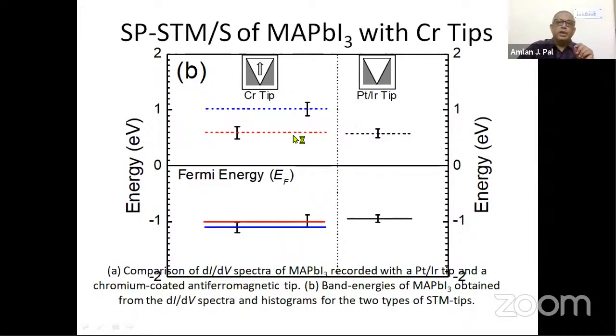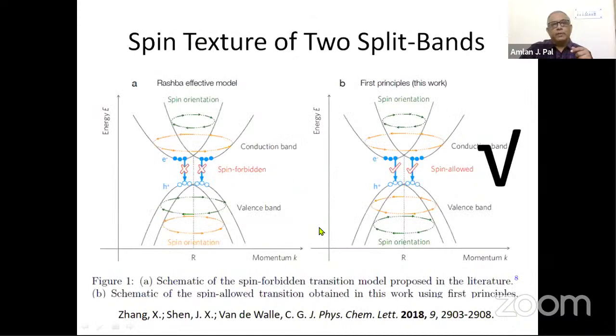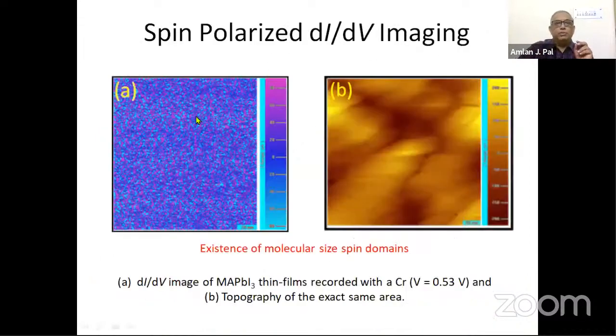We found that if we do one measurement, we get these red levels, and in the next molecule, we see the blue levels. That is, the domains are just molecular in nature. That is best viewed if we do some kind of imaging. If you look at this imaging, the scale here is 20 nanometer scale. So that's the dI/dV imaging. This tells us about the domain of the molecules here.